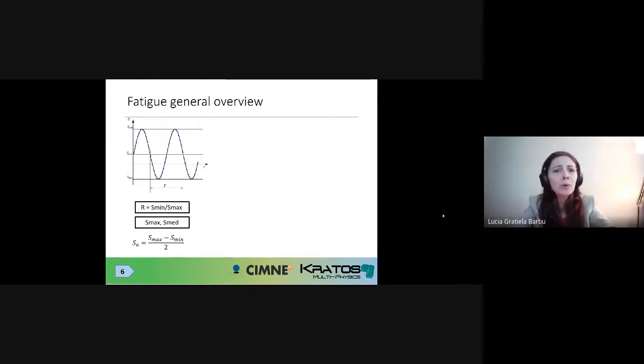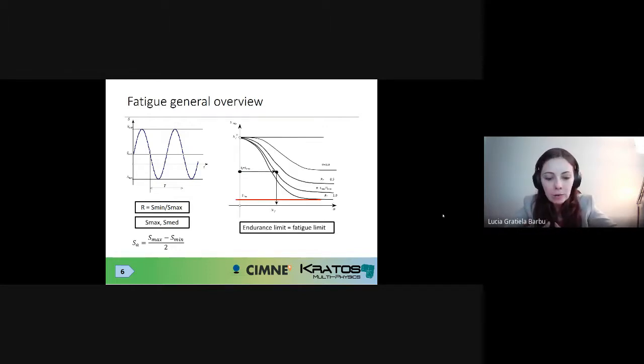Then, what's also important for fatigue formulations, especially in the high cycle fatigue domain, is the maximum level of stress recorded either at each integration point or in the whole geometry. Also, the mean stress, the medium level of stress recorded, because here you can have different types of cyclic loading. For instance, completely oscillating, where you have zero mean stress, or you can have tensile mean stress, etc. Also, you can record the amplitude of the cyclic loading and of the stress state induced by the cyclic loading. I want to be precise here.